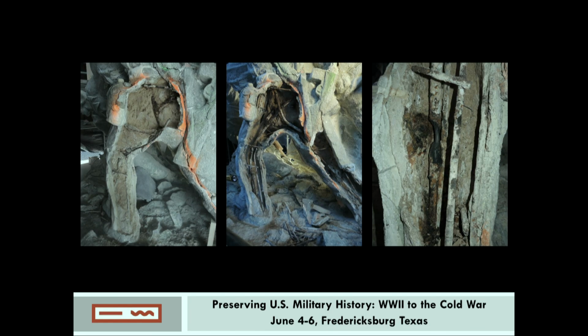and the lower legs. Rebar showed extreme levels of corrosion with more than 50% of the bar thickness reduced. You can see this on the right image, which is the left leg of Schultz. Rebar that were embedded in the wall of the concrete shell for structural support were often completely disintegrated. Some sections of rebar simply fell out when we opened the sculpture. You can see the really thin section there. That was probably 1-inch rebar.